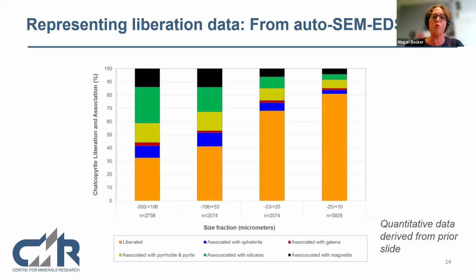I can then go and quantify that, and here plot a graph showing chalcopyrite liberation and association by different size fractions. It's also very important that I report the number of particles I've measured, because if you're looking at this data set and you see 10, 20, 30, 40, you might not have as much confidence, whereas if you're seeing particles in the hundreds and the thousands, you have more confidence in the data set that is more representative.